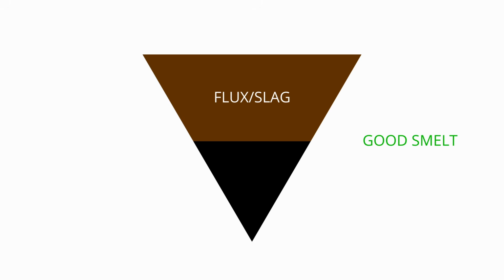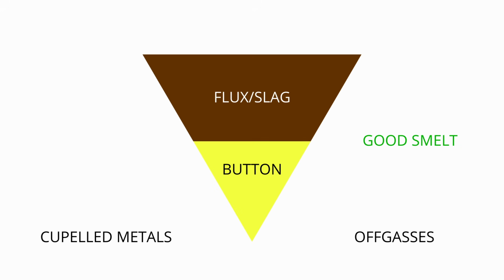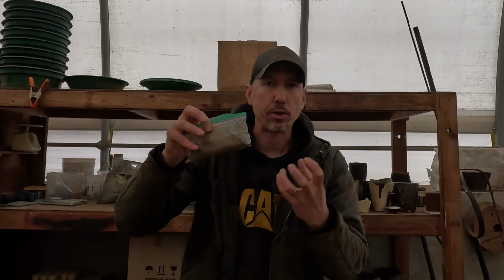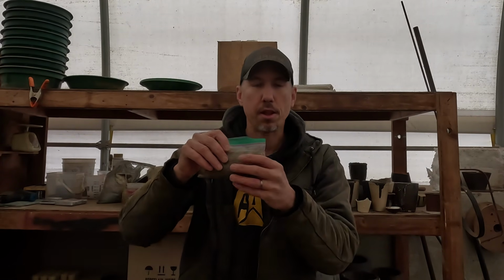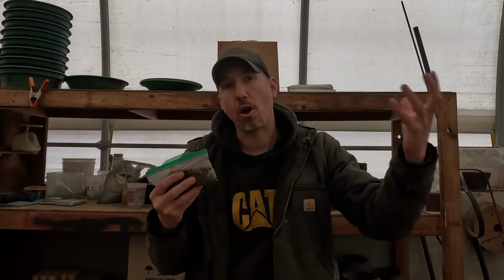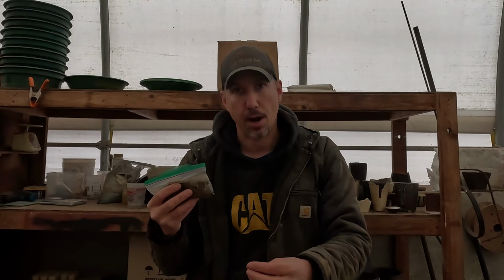So the ideal smelt is a nice glassy or intermediate slag layer, and then a metallic button that separates pretty easy from the slag. The whole point of the smelt is to take all this junk that we don't want. We just want the gold and silver in here, and we got to use chemistry to convert all of the particles in here to be absorbed by the slag, and then all the precious metals to end up down in the bottom of the button.